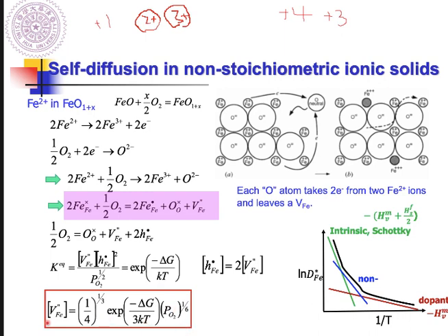So now we already know the vacancy fraction at the iron side, so we can successfully just substitute this term to get the DFe. So when you try to know the slope for this non-stoichiometry effect, it will include this enthalpy term, and also the migration energy part. So including the migration energy and this term. Okay.